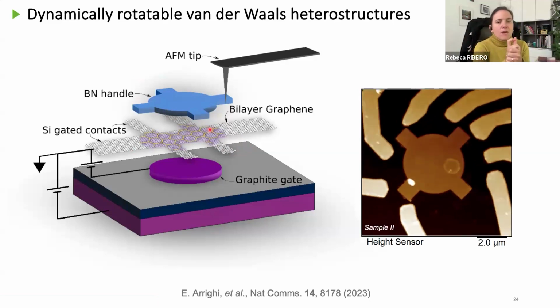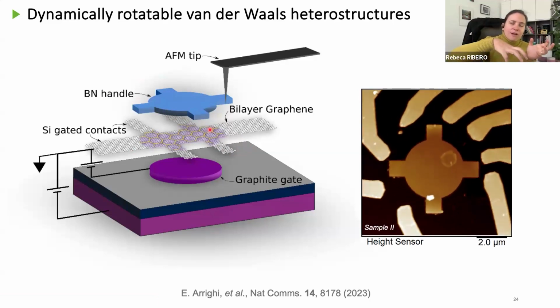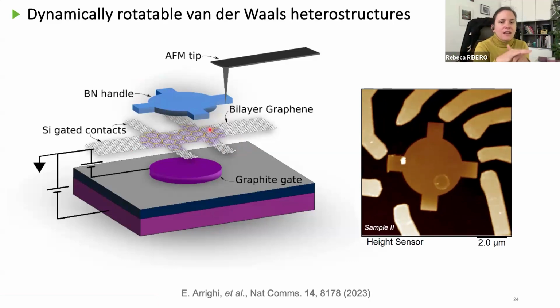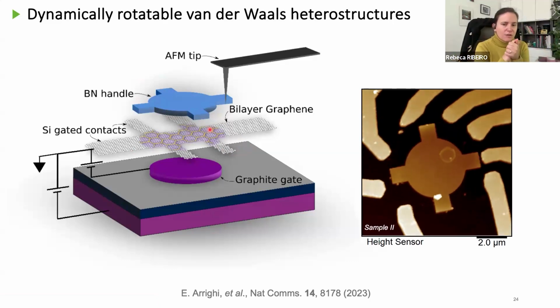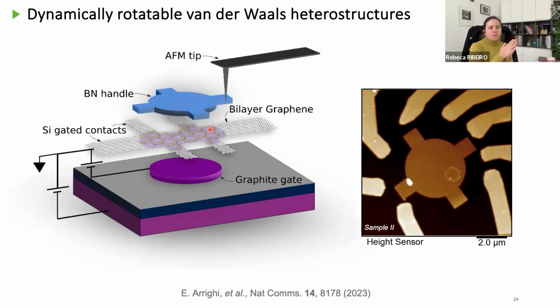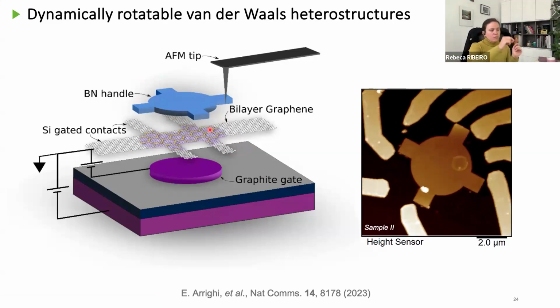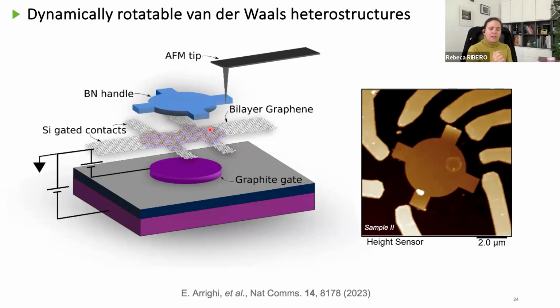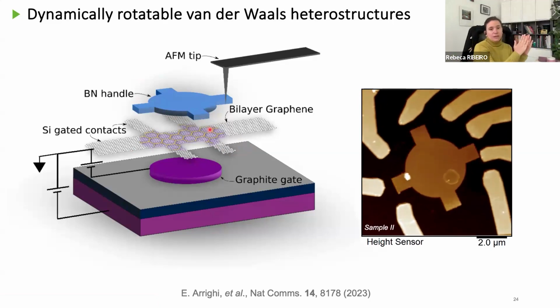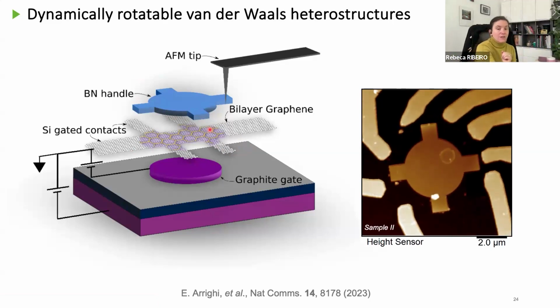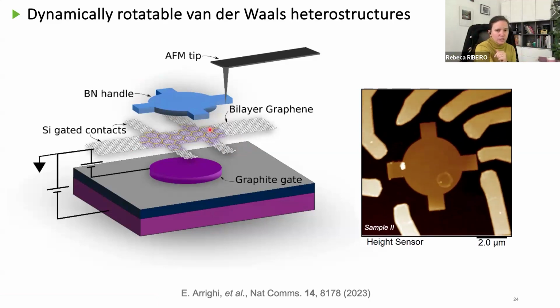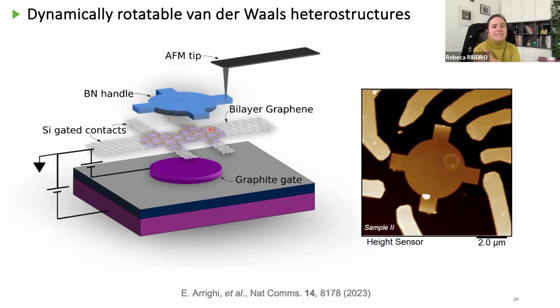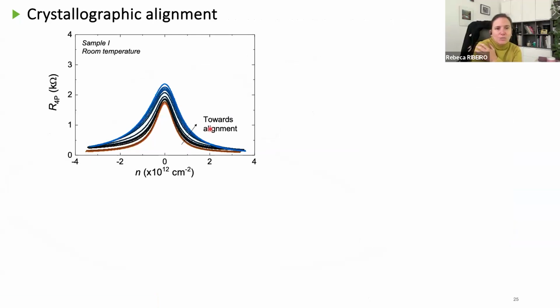The technique is the same. We still use the AFM to push this handle around and therefore change the crystallographic orientation. So if you remember, before, at room temperature we could see this very prominent peak that we call the satellite peak, moving with the crystallographic alignment, moving in gate voltage. Now the case for bilayer graphene is slightly more complicated. In this one, we do not see the presence of any satellite peak at room temperature. There is nothing. This is very well understood.